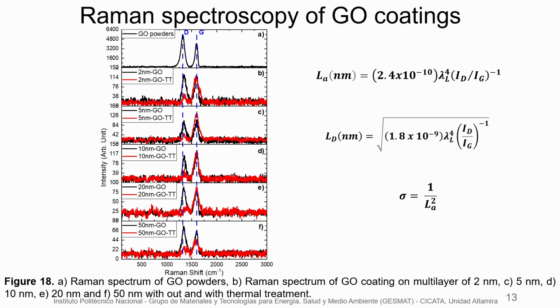After thermal treatment, we can see that the D band almost disappears, and this is related to the reduction of the graphene oxide when it releases the oxygen groups, and possible restoration of the sp2 character of the graphene lattice. But we also can see that the G band, which is related to the graphene skeleton, is distorted: the full width at half maximum is increased, and there's a distortion and shift of the G band. This is attributed to a fragmentation of the graphene sheets during the thermal treatment, which will be discussed later.